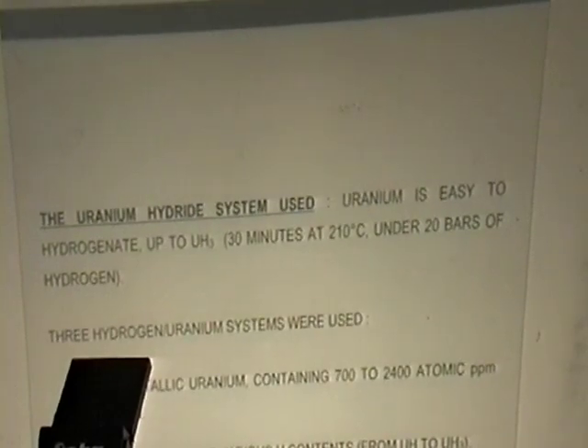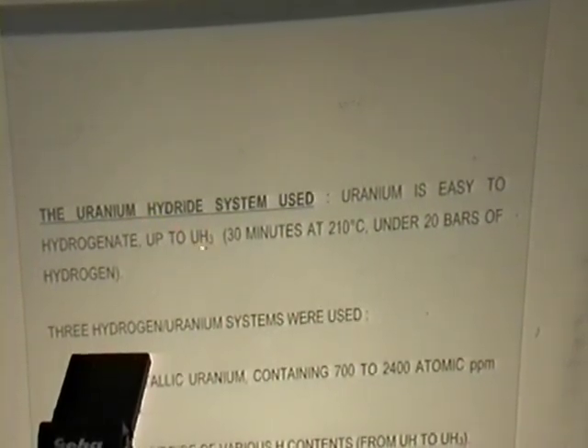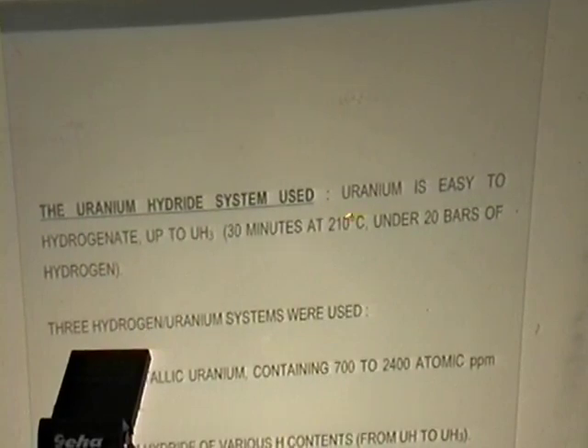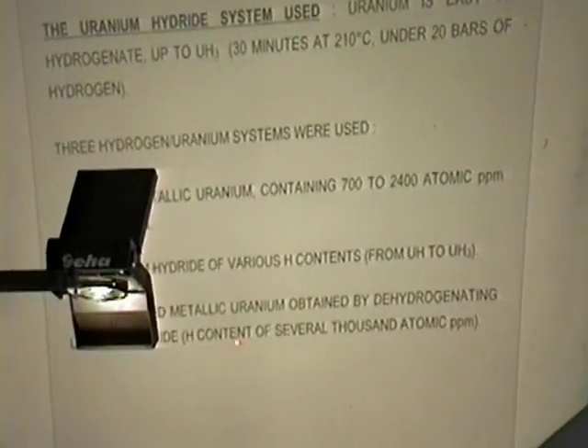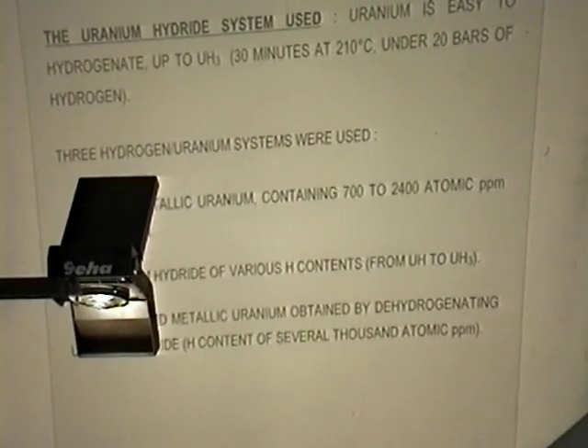Of course, we are speaking of the hydrogen uranium system, so we are using uranium hydride. Uranium is very easy to hydrogenate. You can reach UH3 very easily, in 30 minutes at 210°C and 20 bar of hydrogen. We have studied 3 hydrogen uranium systems. One is solid metallic uranium as such, which always contains between 1,000 to 2,000 or 3,000 atomic ppm hydrogen; uranium hydride of various hydrogen content; and powdered metallic uranium obtained by dehydrogenating uranium hydride down to 1,000 atomic ppm hydrogen.